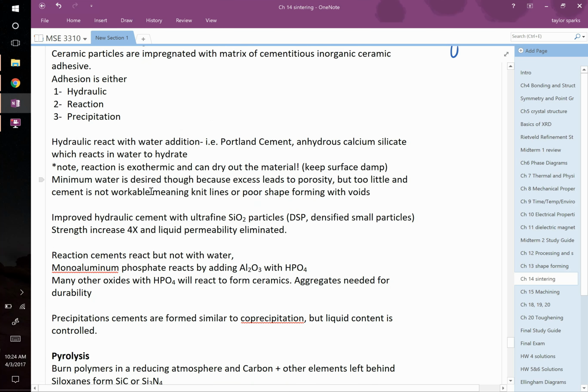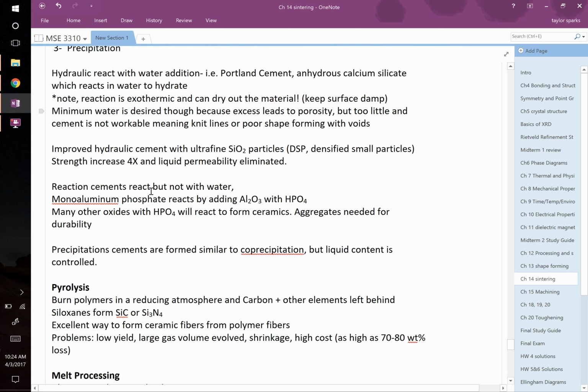But okay, 5 more minutes. Let's keep going. There's other methods though, so that's a hydraulic cement. There's also reaction bonding. This was my whole 2 years of an internship at Ceramic Tech: reaction bonded aluminum phosphate. You start out with alumina, you add phosphoric acid, it bonds to form AlPO4, right? And it gives off water as it does so, because that hydrogen's got to go somewhere, and there's a little bit too much oxygen as well. So it gives off water, and it forms this aluminum phosphate ceramic. That's another way. Lots of those.